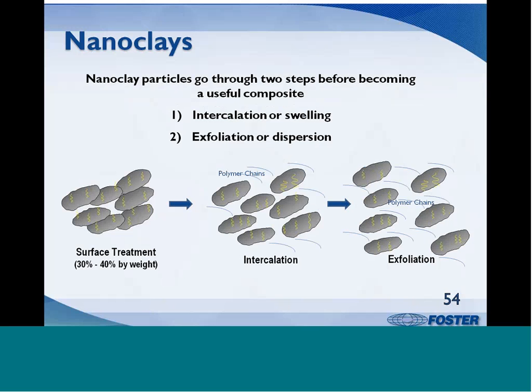After surface treatment, the particles will be mixed with the polymer under some level of heat and shear. The particles will swell, and the polymer chains will start to move into the gaps. With exfoliation, dispersion down to the primary particle is accomplished.